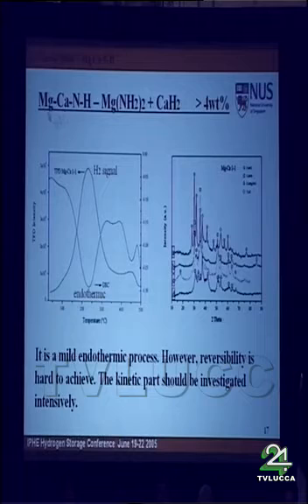We also look at the magnesium calcium nitrogen hydrogen system because we want to get rid of lithium. We hope this system could show certain reversibility. However, although the hydrogen desorption amount is pretty good, and we also observe an endothermic feature in hydrogen desorption, the reversibility is hard to achieve. We think it's probably due to the kinetic barriers. We are working on that. In this chemical reaction, we also observe new phases, a new kind of imide formed after hydrogen desorption.